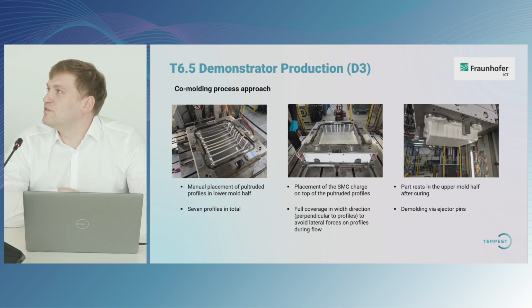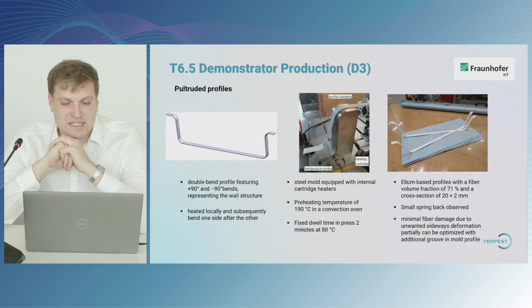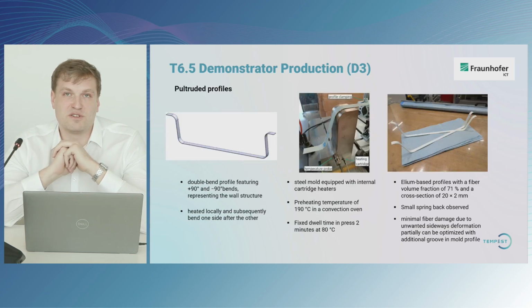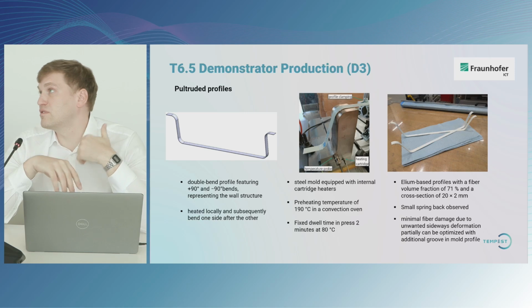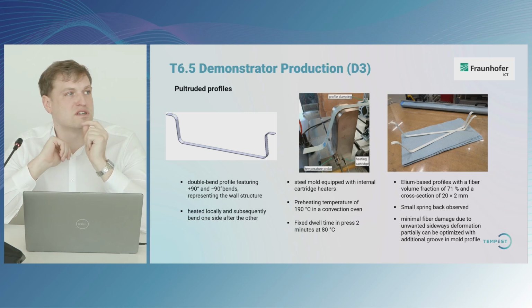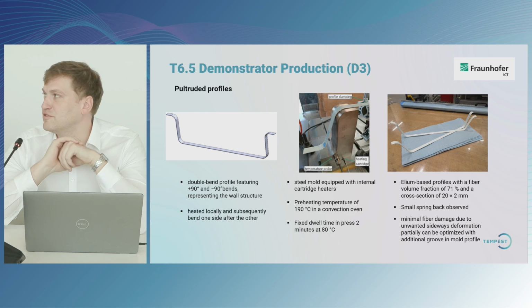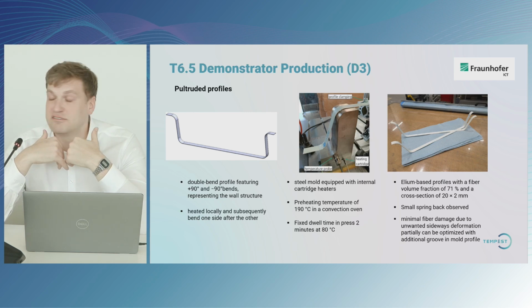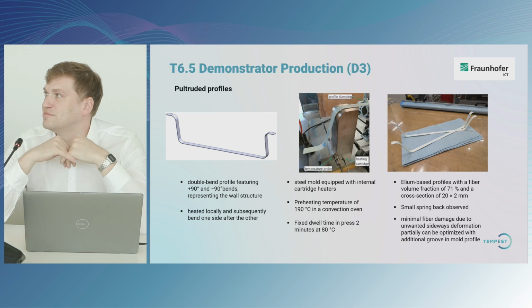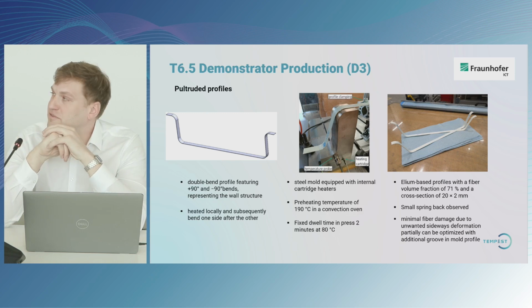The special thing about this is that compared to other approaches with prepreg, with metallic hybrids, we have only one single material used here, still achieving a higher stiffness. So in perspective to recycling, it's one material, you can recycle it really well. And if this works well, you really achieved something.